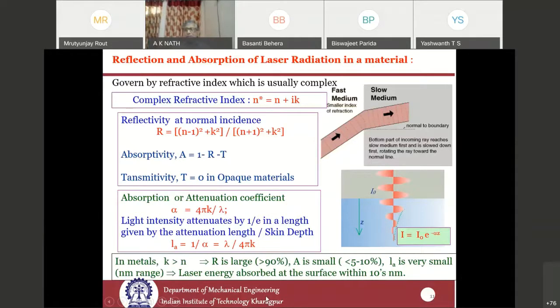So what does it mean? It means that whenever the laser beam is incident, most of the laser power gets reflected from the surface. A very small amount is absorbed at the surface, and this absorption takes place within a very small depth, around 10 nanometers. So basically, the laser power is absorbed on the top surface, and heat penetrates inside the material, and through heat conduction, the material gets heated up.